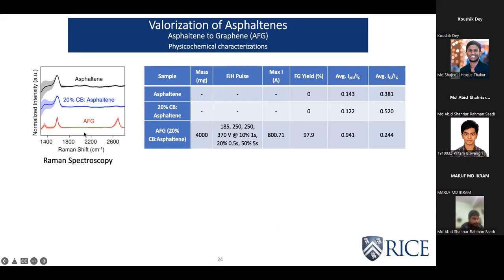And Raman showed that for AFG, which is the asphaltene flash graphene, there was the development of this 2D peak around 2700 wave number. So this gave us the idea that graphene has been formed, but we had to double check using other characterization techniques as well.